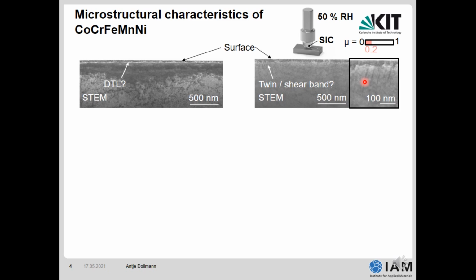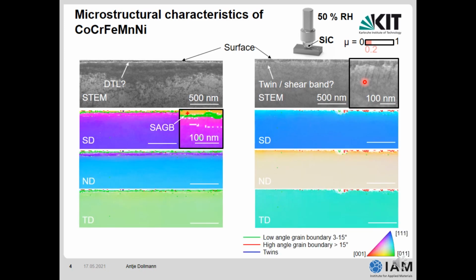To further investigate that, I have done TKD measurements. TKD means transmission Kikuchi diffraction, and it's the same technique as for EBSD. So both of the TKD measurements are shown here in sliding, normal, and transverse direction. Furthermore, I have plotted low angle grain boundaries in green, high angle grain boundaries in red, and twins in blue. So in the first grain, we see here this small angle grain boundary. So this is again a higher magnification of the surface near area.